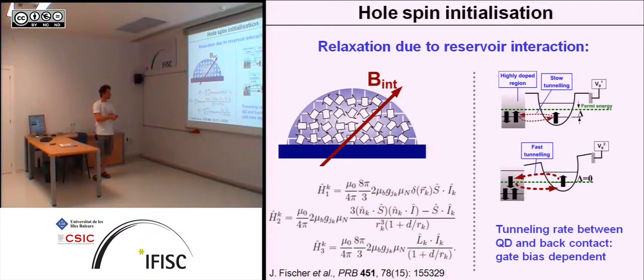And you can now have interaction on the single atom level, or you can have interaction with the overall field, because tens of thousands of atoms is pretty unfortunate: if it were millions, then you wouldn't have a preferred direction of the magnetic field, because it would just average out. But there are too many to really control each one of them individually. So if you just look at the magnetic dipole-dipole coupling between a nuclear spin and the spin of a carrier inside this quantum dot, you can split it up into these three terms.